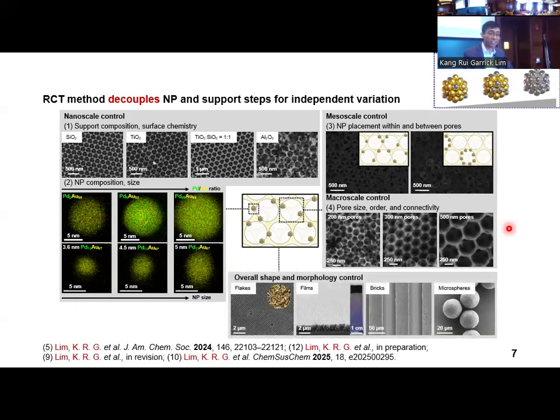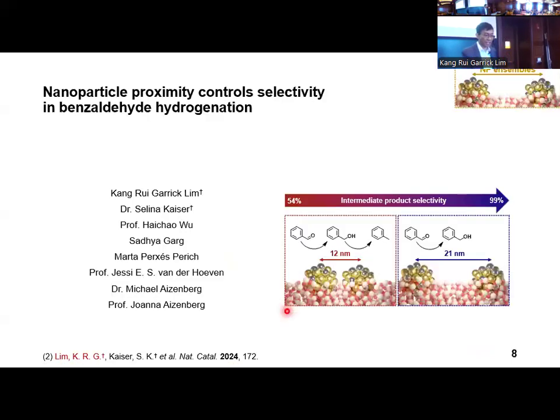Finally, the RCT catalyst can be fabricated on a variety of preformed catalyst support surfaces as films or bricks, or take on discrete standalone shapes like microspheres and freestanding flakes. Beyond the individual nanoparticle properties, the RCT method allows us to control properties of the nanoparticles as a collective entity, such as the interparticle distance and the nanoparticle localization. In this first half of my talk, I will illustrate how nanoparticle proximity as a collective ensemble property can be used as a mesoscale tool to direct our reaction selectivity.